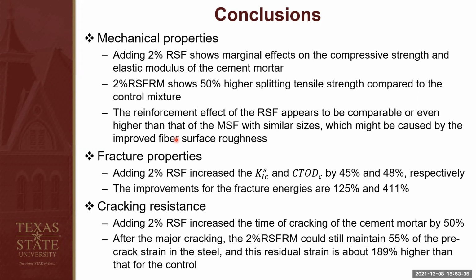And we believe this improvement or equivalent performance was caused by the improved fiber surface roughness due to the residual rubber. For the fracture properties, adding 2% recycled steel fiber increased the stress intensity factor and the critical crack tip opening displacement, and the fracture energy were also improved significantly.